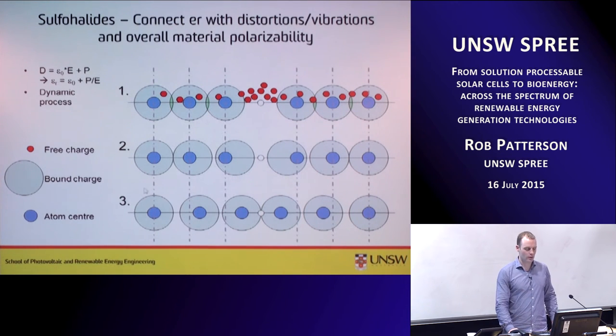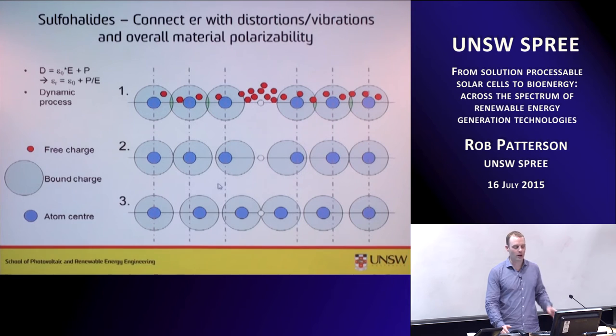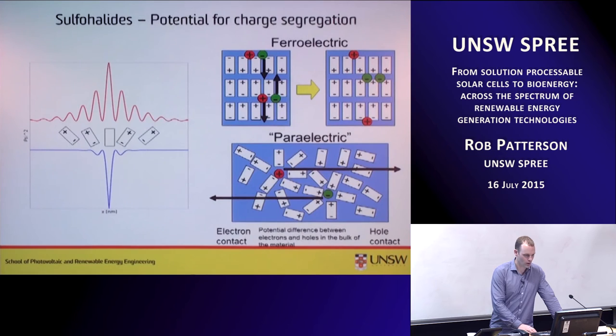And deformations are another way to do this. Potentially, you can have these things getting passivated. And then maybe at grain boundaries, for example, this can be an advantage. So in ferroelectrics, this has been discussed actually by the group in Bath. Potentially, you can have segregation of charge carriers to domain walls in the ferroelectric. And this potentially means that these negatively charged carriers are going to move along this domain wall here, whereas the other ones are forced to move along other domain walls.